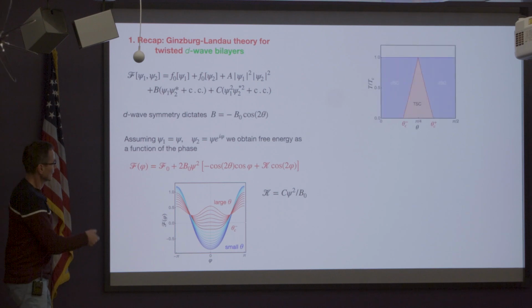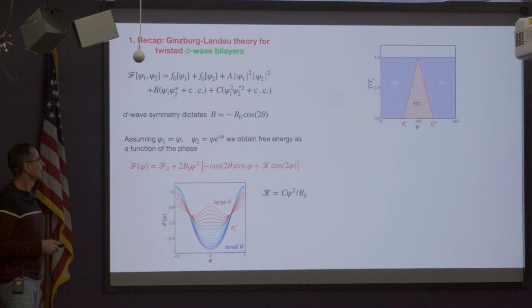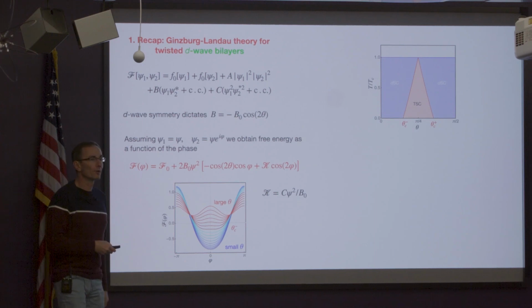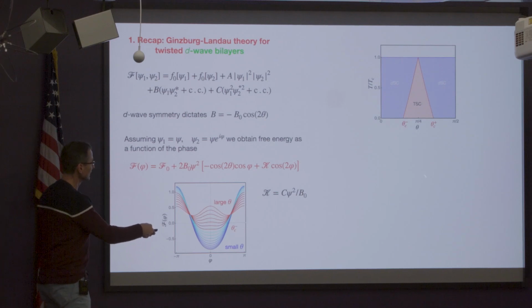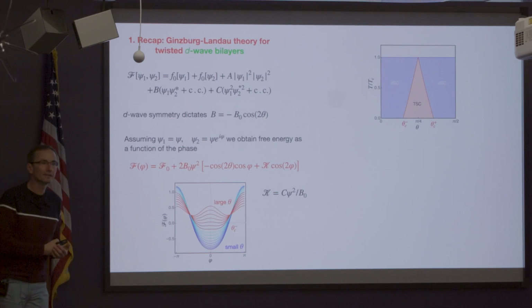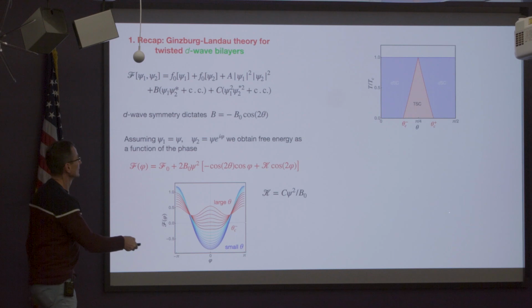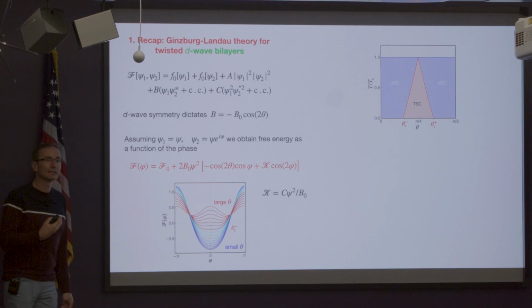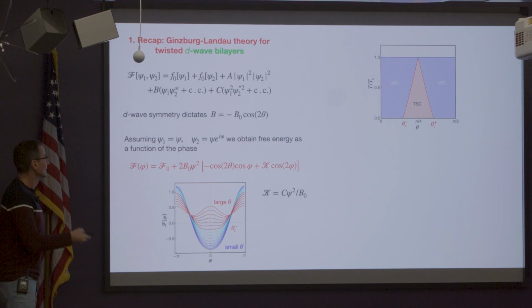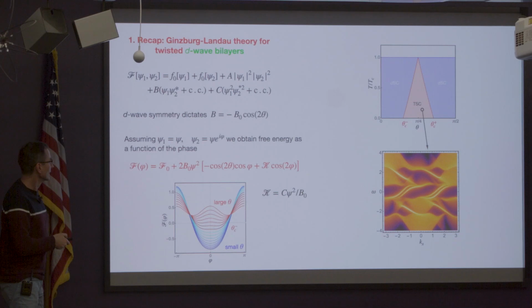twist angles. A phase diagram in twist angle temperature plane looks something like this, where there's a wedge of this topological superconductor, and interestingly, at exactly 45 degrees, this phase extends all the way up to the native critical temperature of the monolayer, which is potentially 90 degrees in BISCO or thereabouts.